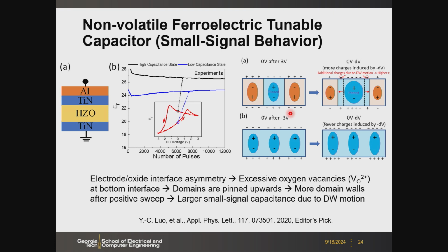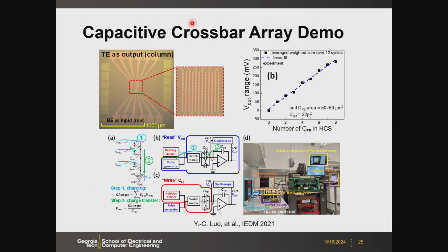So this is, of course, a hypothesis. We have done some modeling to back up this mechanism, but of course, there's no direct evidence. Right? This is what we assumed. But anyway, we can successfully create this window, even though it's kind of small, but we can have high and low capacitance states. The key is to have the CV asymmetry, okay? So with this device, we further integrate that into a crossbar array. And with a probe card system, we can demonstrate some of those charge domain transfer mechanisms we proposed earlier.